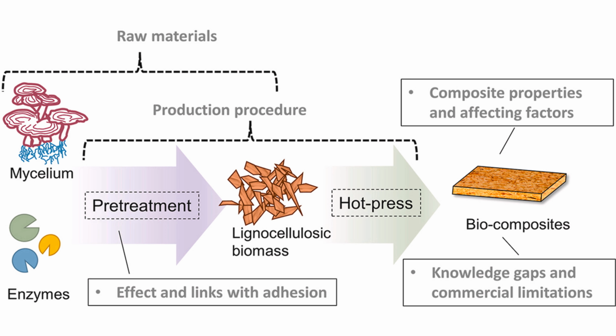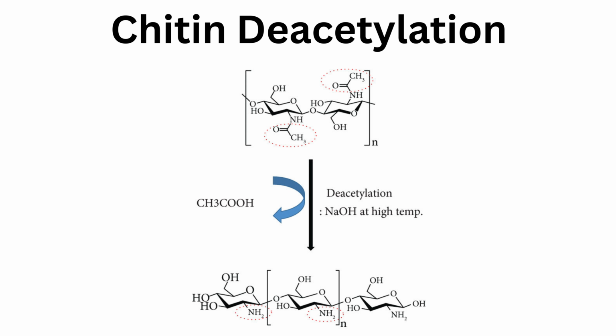necessary. The chemical pretreatment process has been noted to either be a mild alkali or acid treatment, and these are both synonymous with the liming pretreatment in animal skin leather, which serves to remove extraneous materials while enhancing the subsequent penetration of the tanning agents. The modification of the chitin content of the fungal mycelium has also been identified as a viable avenue for the introduction of chemical modifications, thereby enabling new properties.